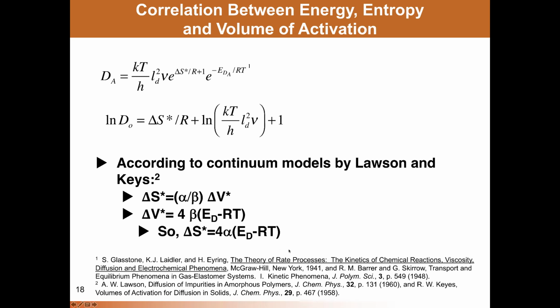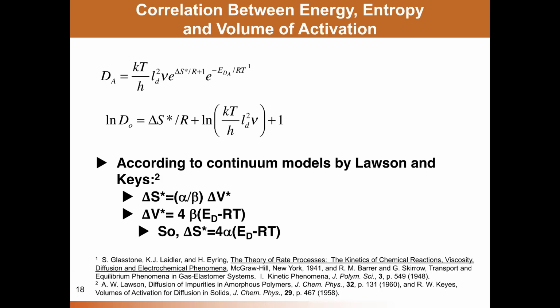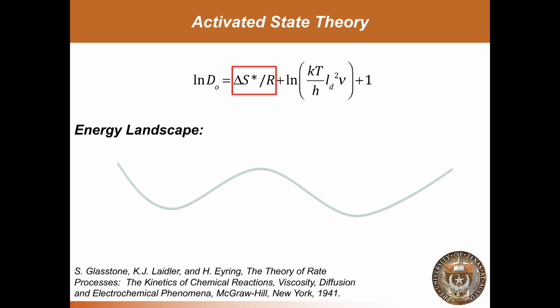entropy of activation. And in the context of this model, one should expect that the activation entropy and activation energy are correlated, and that would lead directly to the linear free energy relation shown here, because the log of D0 is proportional to the entropy of activation.